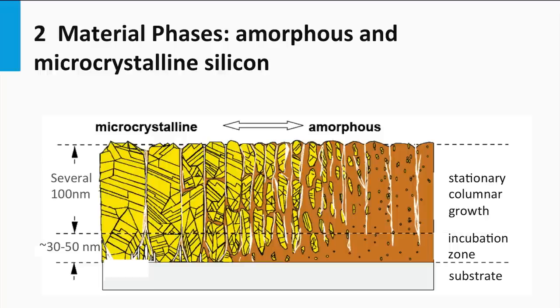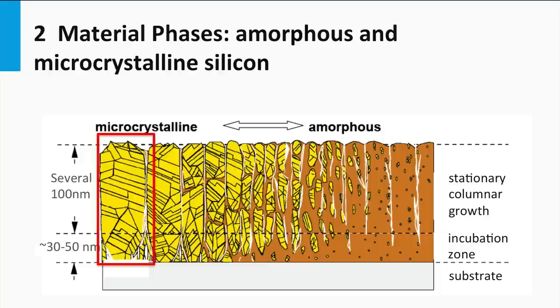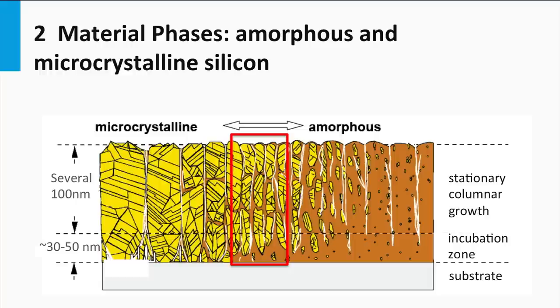This illustration, made by the Forschungszentrum in Jülich, Germany, shows the various phases of thin film silicon going from left to right. At the right-hand side the phase represents the amorphous lattice. At the left-hand side a fully crystalline phase is shown, close to that of polycrystalline silicon, except that it has much more cracks and pores. Note that nanocrystalline and microcrystalline silicon refer to the same phase. Going from right to left, the amorphous phase changes into a mixed phase with a few small crystalline grains, to a phase dominated by large crystalline grains and a small fraction of amorphous tissue. The best nanocrystalline silicon bulk materials used in solar cells have a network close to the amorphous-to-nanocrystalline transition, with a crystalline volume fraction in the order of 60%.